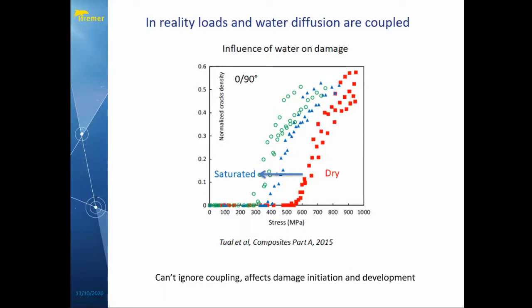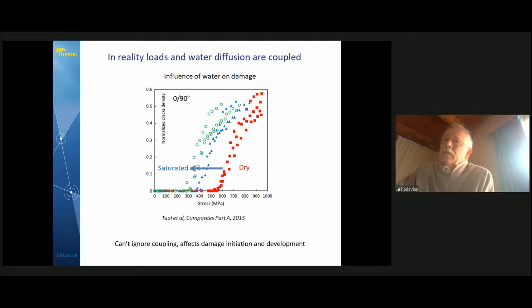And more important is that saturation is one parameter. We have water present throughout the material, but if you continue the test and leave it for longer times, the material can degrade further. And these are the green points here. We had, after 1, 2, 3 months of saturated state, an even lower value around 250 MPa. So as this damage goes into the material, the water ingress parameters also get affected, and we get a continuing drop in properties.